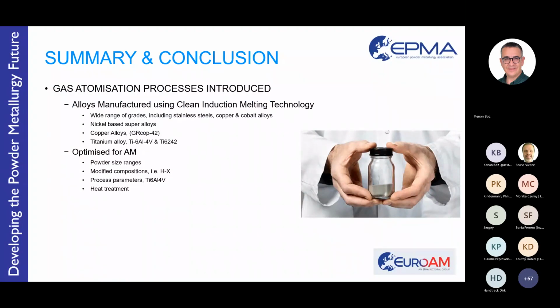Materials are manufactured using clean induction melting technology, incorporating a wide range of different materials, from stainless steels themselves incorporating a lot of recycled material, copper alloys, cobalt alloys, as well as classic nickel-based superalloys, copper and copper alloys, including the GRCop-42, and titanium alloys, including new alloys like titanium 6242, which are now available in powder form. These have all been optimized for additive manufacturing in terms of powder size range, modified compositions for the process, like the example of Hastelloy X.